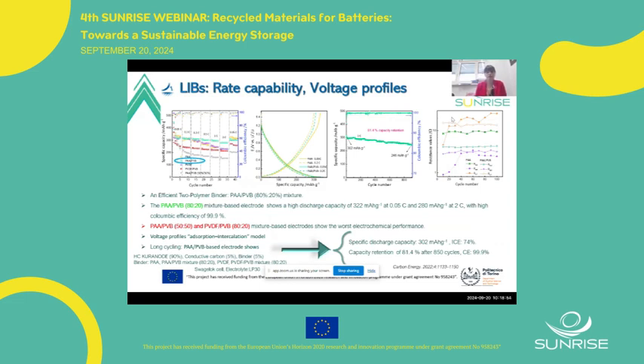Also, we tried to increase the amount of PVB to 50%, meaning PAA-PVB 50-50%, but as you can see, the gray one, we lost a lot of capacity during the initial cycle. So it's not a good idea to increase the amount of PVB to 50%.